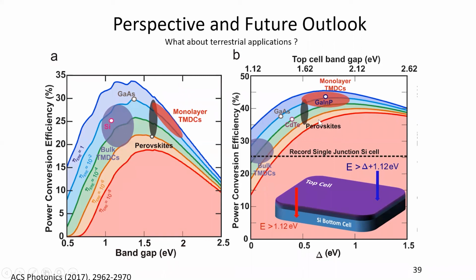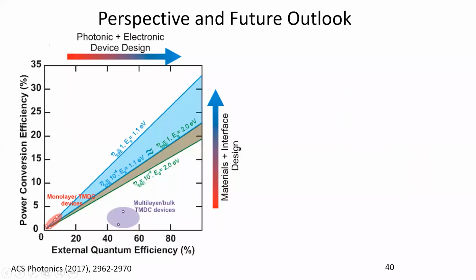This is also one of the main reasons why solution processed perovskites have had a huge advantage in terms of integrating on top of silicon. They don't need to be epitaxially grown in high quality like, say, gallium arsenide or gallium indium phosphide. That's a big advantage. So if you look at the current perspective of where the devices are lying